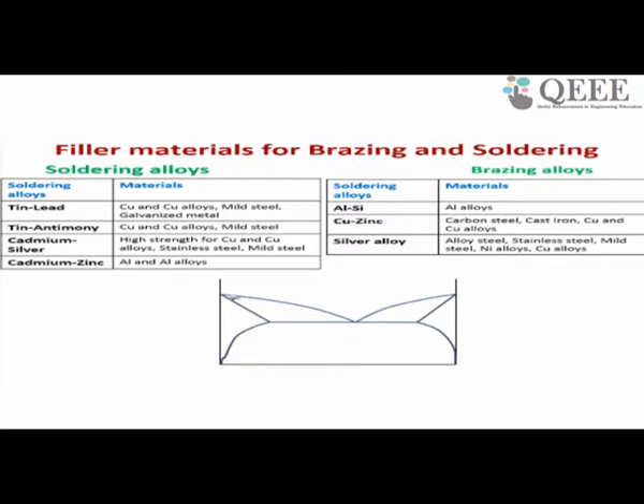Then the filler material. As we know, for soldering the melting point of the filler material should be less than 450 degrees centigrade. Similarly in brazing, the brazing is happening at above 450 degrees centigrade. So the process will happen above 450 degrees centigrade here. For example, there are different soldering filler alloys. Tin lead based filler material is used for copper and copper alloys, mild steels, galvanized steels, etc. And tin antimony alloys are used for copper and copper alloys, mild steels, like that.